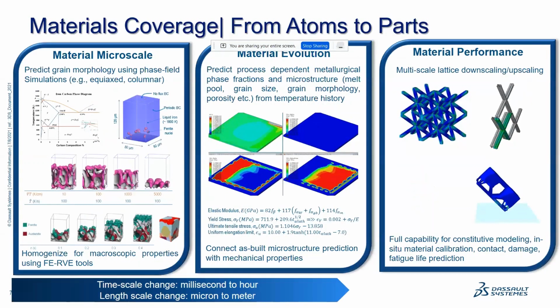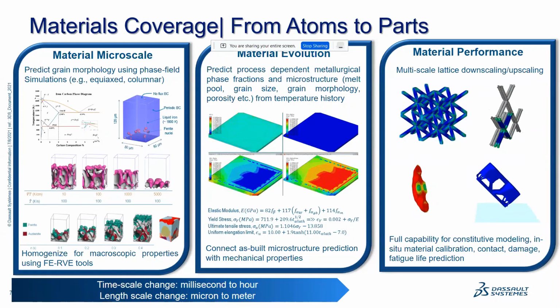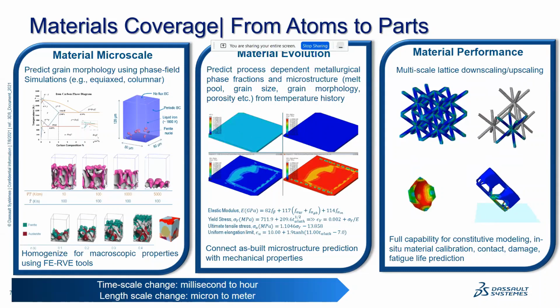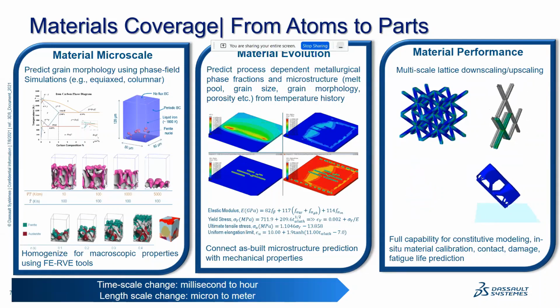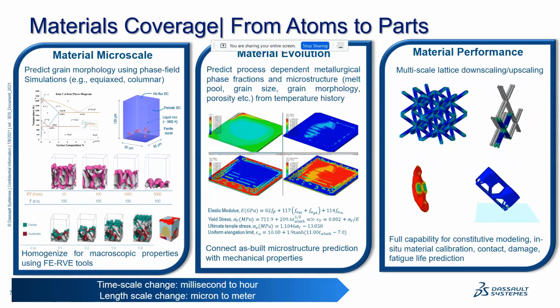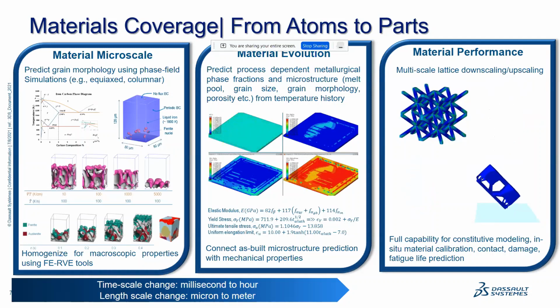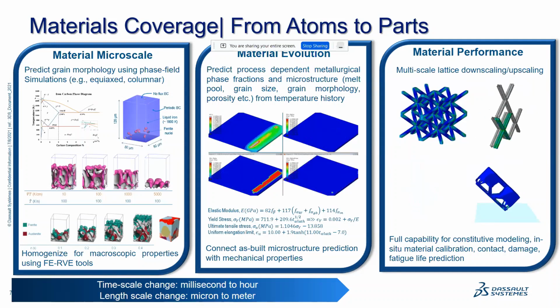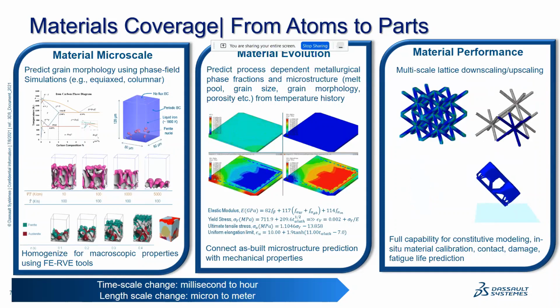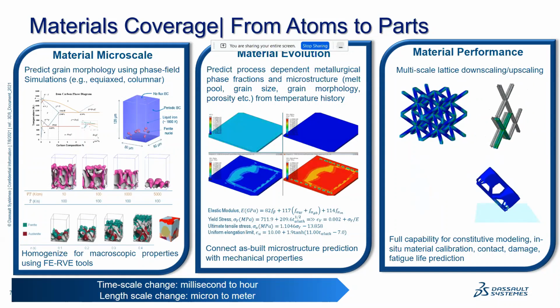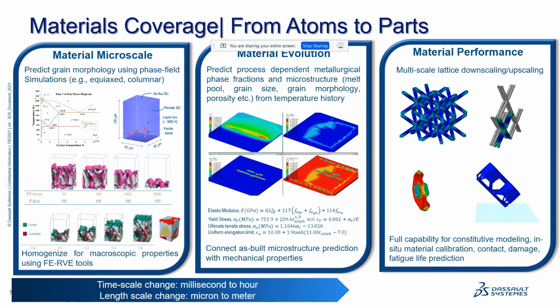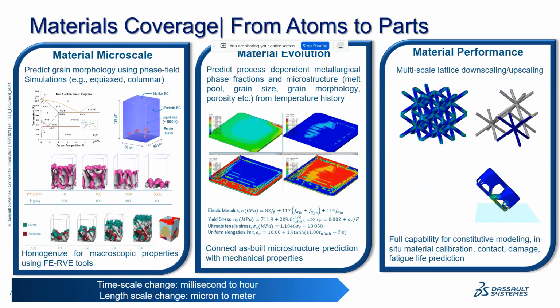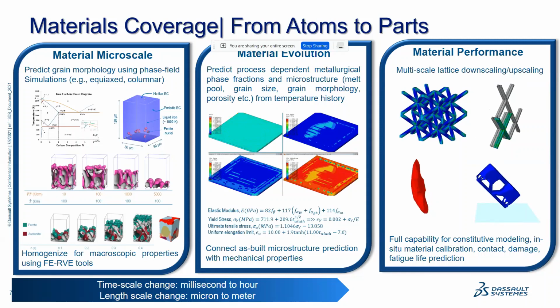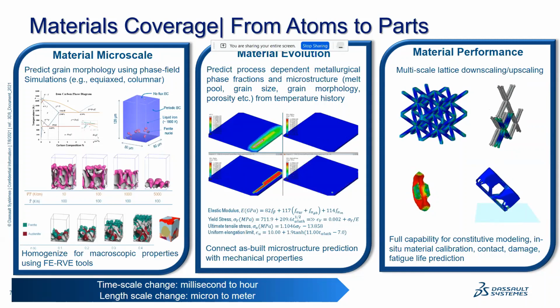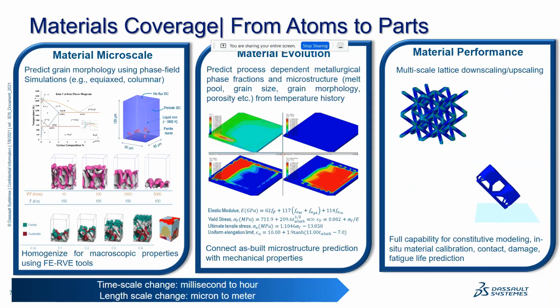So here we show some of the details in terms of the validations that are being done. So one is to validate the behavior according to a material microscale model, where we do some phase transformation RVE based simulations. The next part is on evolving or modeling the phase evolution. So you have certain kinetic phase functionality equations which need to be modeled to predict the melt pool or the grain size evolution. And the third part, which we'll talk about towards the end, is on the material performance, where we can create lattice structures by form of replicatable or repeatable patterns, which are useful in terms of lightweighting as well.